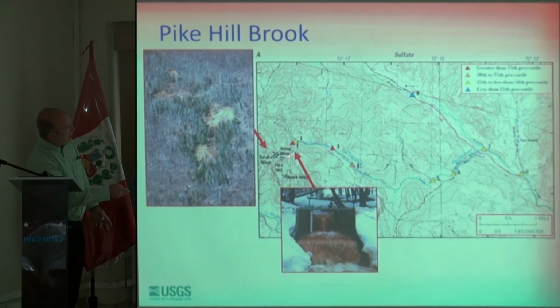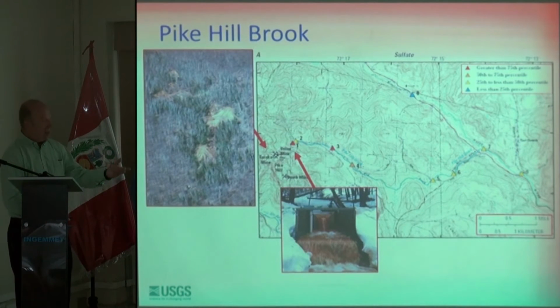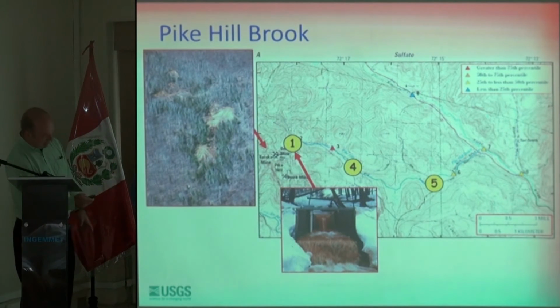We installed a weir at the base of the stream, so this is what it looks like with spring melt. You can see the acid mine drainage and the iron precipitates. We did some monitoring in the stream for over a year at several different sites. We started with the mine drainage input. We had a sample site above this series of wetlands, which falls here, and then we had a downstream site that was conveniently located near the bottom end of the wetlands.